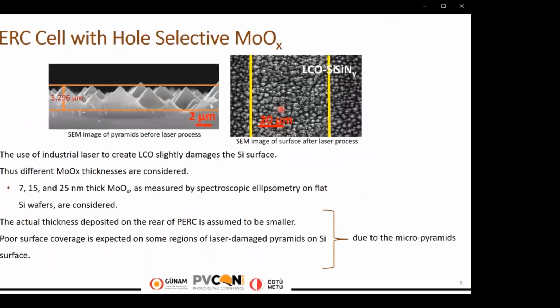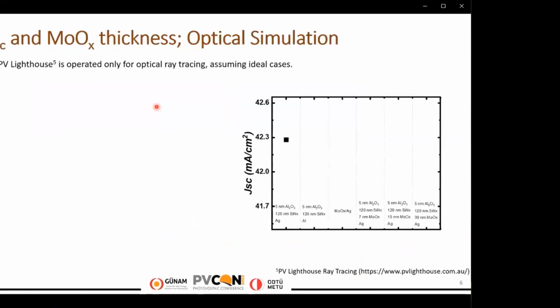The use of an industrial laser to create local contact openings likely damaged the silicon surface, so different molybdenum oxide thicknesses are considered: 7, 15, and 25 nanometer thick molybdenum oxides, as measured by spectroscopic ellipsometry on flat silicon wafers. The actual thickness deposited on the rear of the PERC is assumed to be smaller, and poor surface coverage is expected on some regions of laser damaged pyramids or silicon surface due to the micropyramids, as seen in the SEM images. Three different molybdenum oxide thicknesses deposited by thermal evaporation are considered, and the relation between the thickness and the photovoltaic characteristics of the PERC is investigated.